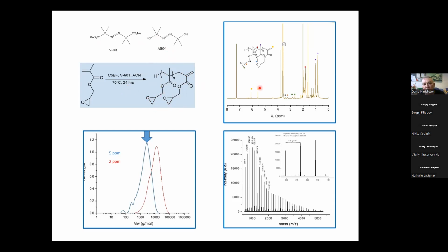And if we look at the NMR, we can see the vinyl group. This is quite a low DP monomer, so it peaks pretty sharp. The vinyl group is slightly different from the monomer, so you can still measure, especially this one here. This little peak here is monomer actually, and this is the oligomer. And again here, this little peak here is some monomer, and then this peak is the product. So we can measure the conversion by NMR, which is quite usual.